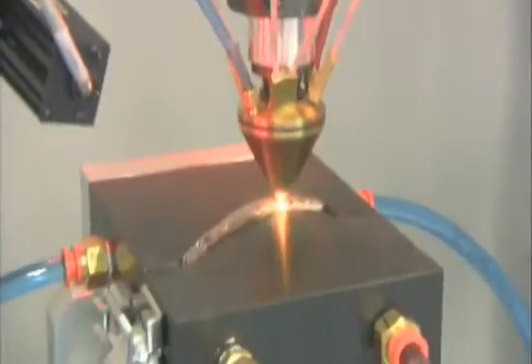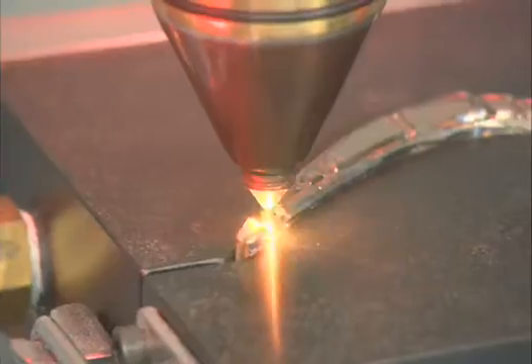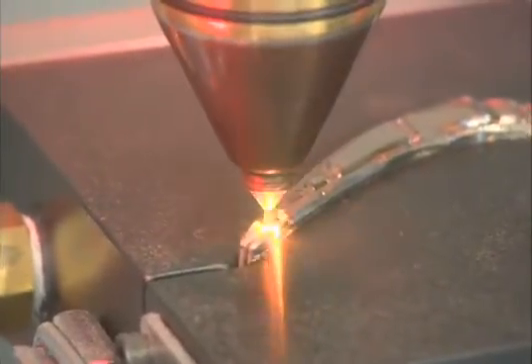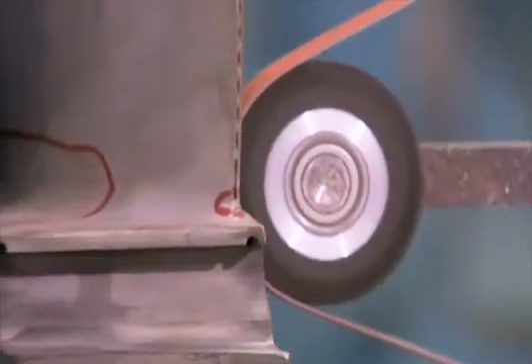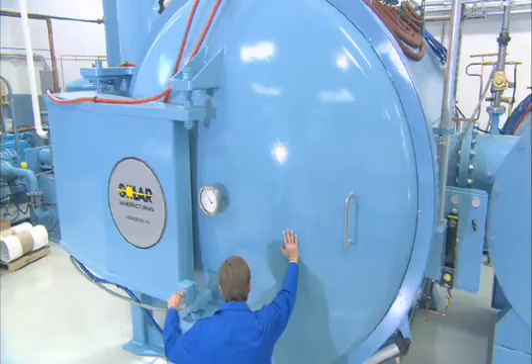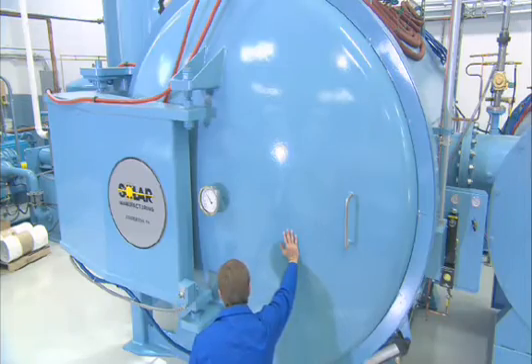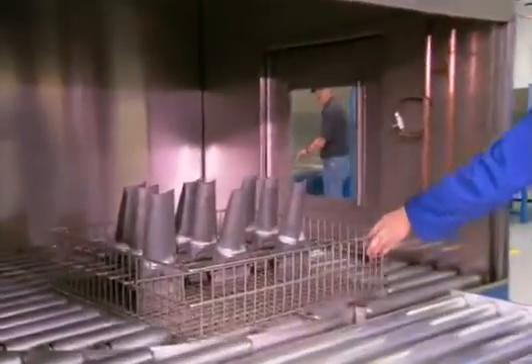This may include tip replacement utilizing laser welding with an advanced vision control system, and leading-edge or trailing-edge coupon replacement involving hand welding by a skilled specialist. Parts are then blended to remove excess weld material and maintain part geometry, dimensionally inspected, then sent through a solution heat-treat process and an FPI inspection to verify the quality of the weld repair.